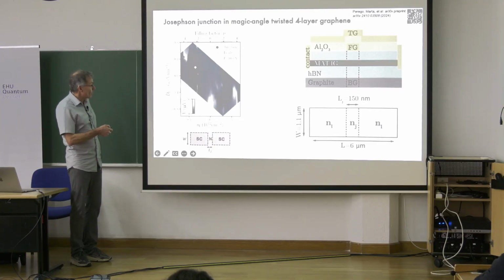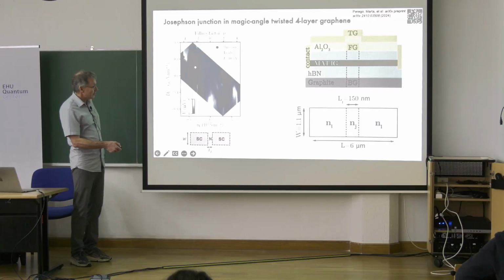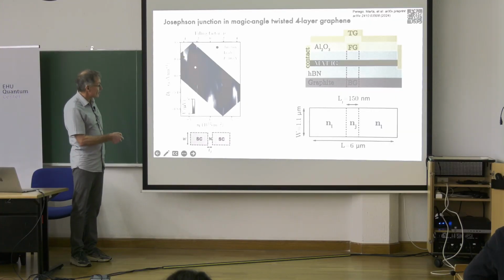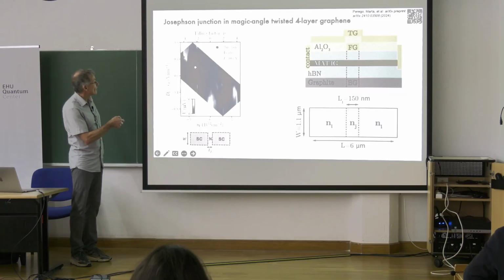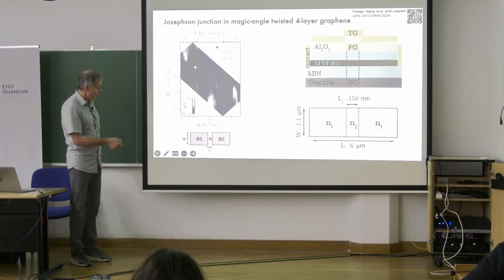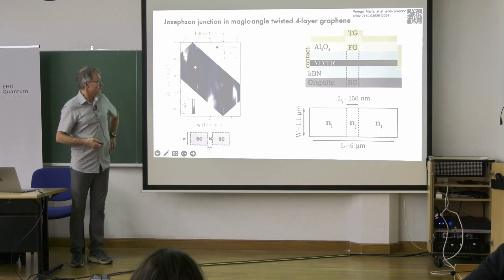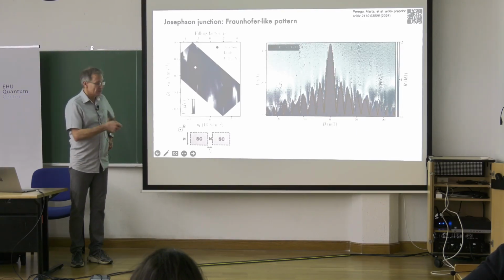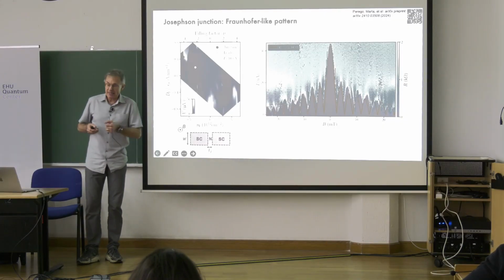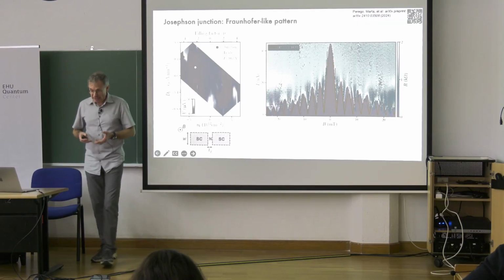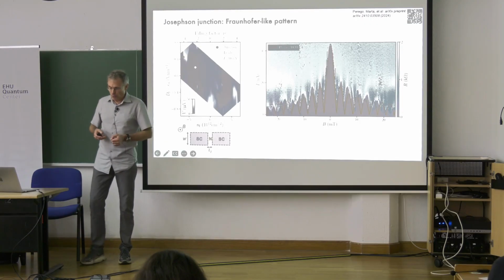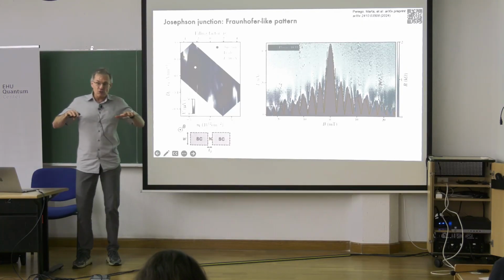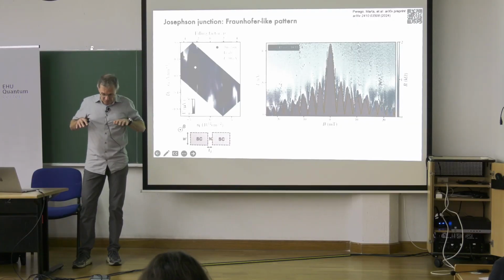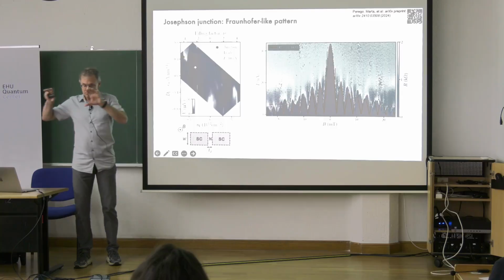So you put gate such that in the leads the resistance is 0, so you tune it to superconducting states. And in the junction, you tune the density of carriers into the high resistive states, and that's how she made the junction. And that's this Fraunhofer pattern which they found. They claim that that's the best Josephson junction made from graphene. Like people use graphene as a weak link between 2 ordinary superconductors.